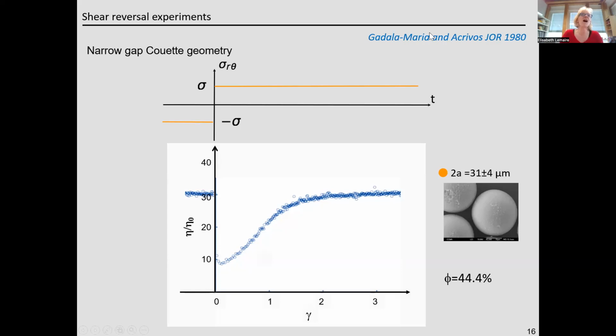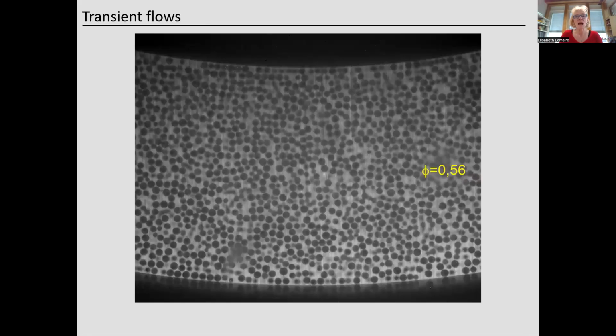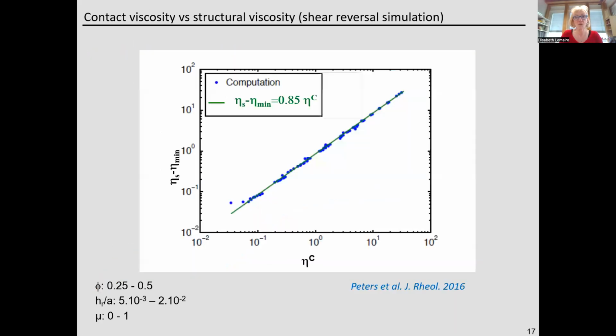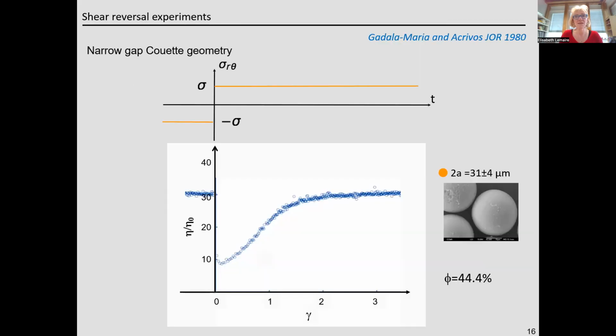When Gadala-Maria and Acrivos proposed this shear reversal experiment, they obtained this kind of answer for the transient viscosity. And for the first time, they explained this transient response of the viscosity by the presence of an asymmetric microstructure in the suspension. And they were right.